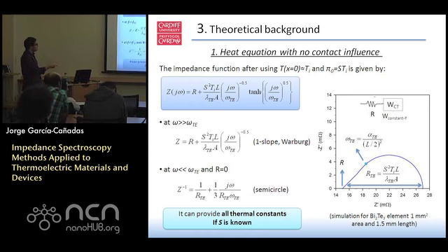Here we see that this characteristic frequency differentiates two regimes of operation. At high frequencies I have the one slope trend, which is given by this approach. As you can see, the impedance function is related as the square root of the frequency. This provides this one slope line.